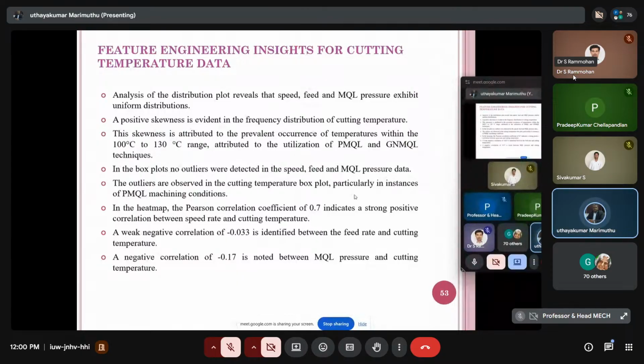In the box plots, no outliers were detected in the speed, feed, and MQL pressure data. Outliers are observed in the cutting temperature box plot, particularly in instances of PMQL machining conditions. In the heat map, the Pearson correlation coefficient of 0.7 indicates a strong positive correlation between speed and cutting temperature. A weak negative correlation of minus 0.033 is identified between feed rate and cutting temperature. A negative correlation of minus 0.17 is noted between MQL pressure and cutting temperature.